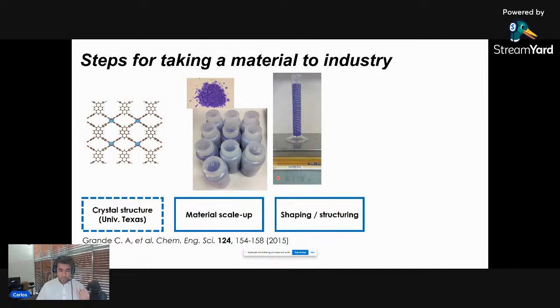The thing is, if you're going to shape it for a very bulk application, probably the simplest thing to do is to pelletize it. There are very simple techniques for doing that. The problem is that when your application becomes very big, when you have pellets, you have a lot of pressure drop. So in that case, you want to have honeycombs. The honeycombs will minimize the pressure drop. If you make these channels a little bit thin, you will not have so many diffusional limitations, and then you can think about having more or less the same performance, but with a lower pressure drop.